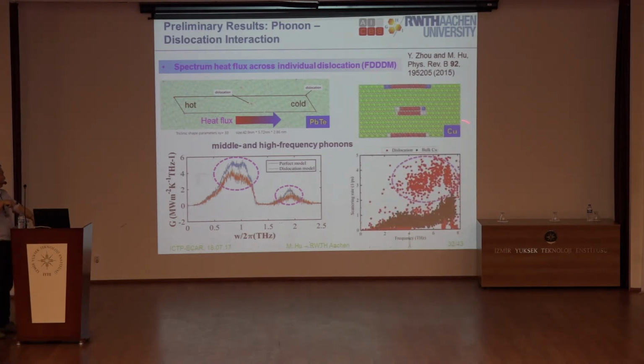So if we do another case of copper, with a single dislocation inside, this is a temporal domain normal mode analysis, and you also find that at the middle frequency and high frequency part the scattering rate will be enhanced, and the relaxation time will go down.